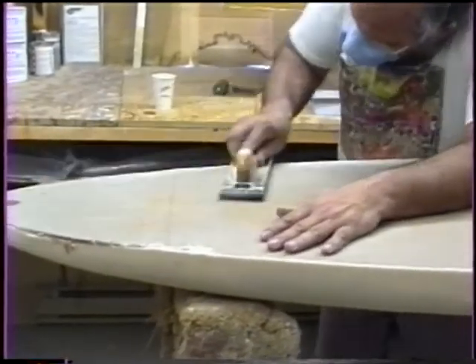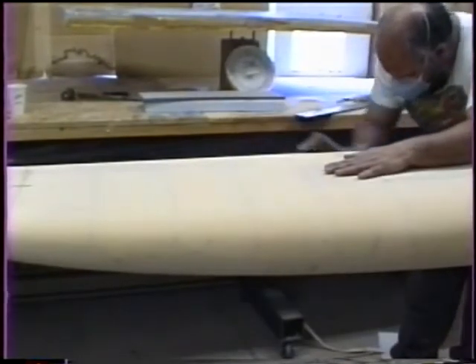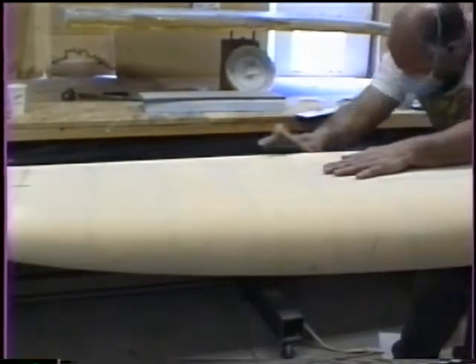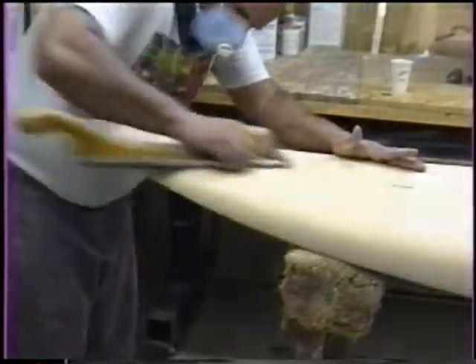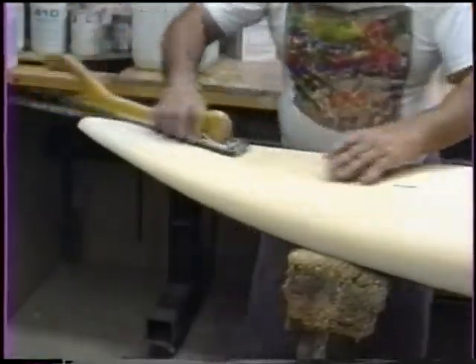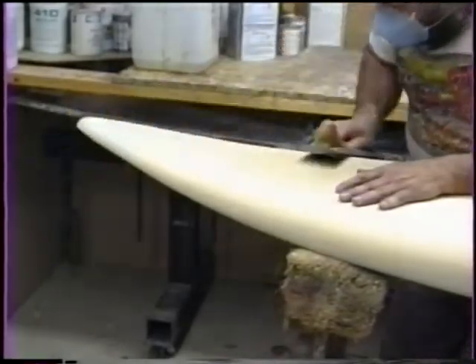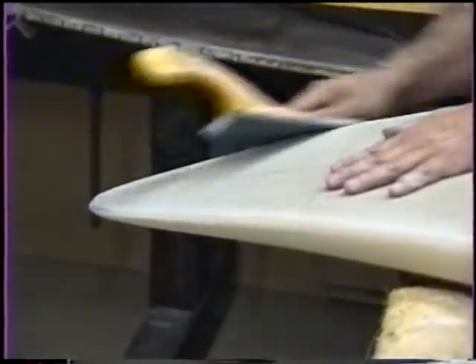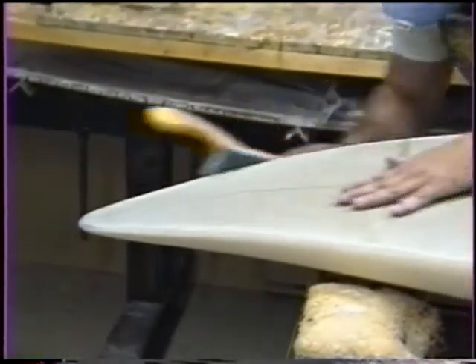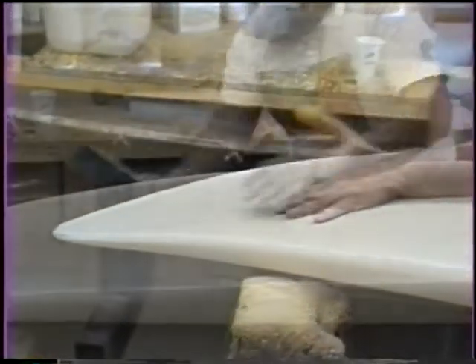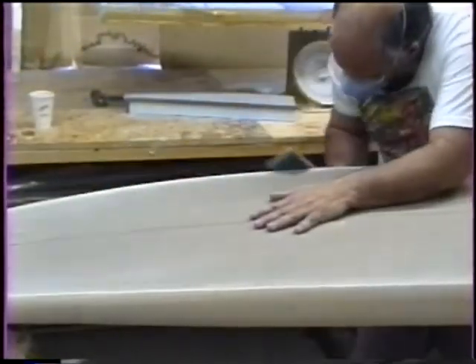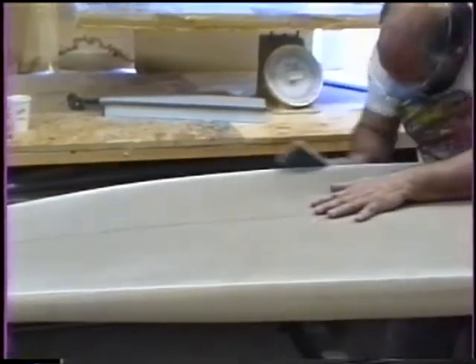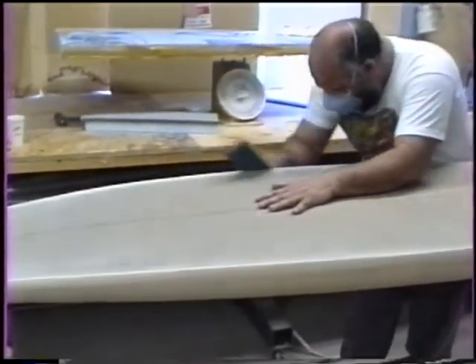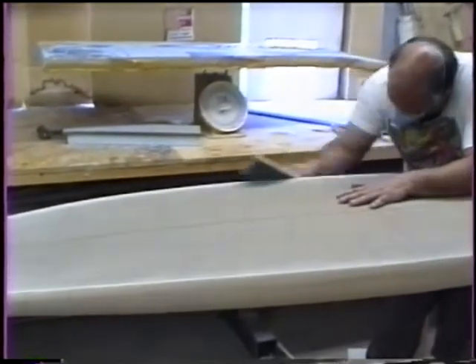Examine and rough sand the blank as required. Fill any low spots, cracks, holes, and joints with a thick mixture of light fairing epoxy. Make sure there is a small hole venting the blank. Allow to heat cure in a warm room or heated box. This will strengthen the bond between the materials. After post-curing, remove and sand the blank with 40 to 60 grit sandpaper on a rigid sanding board, sanding any high points, and continue to refine the shape and rails until you are satisfied.